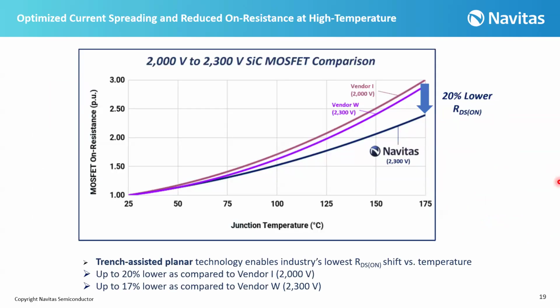Here are the resistance or temperature coefficients from room temperature to 175 degrees C. We compare 2.3 kilovolt Navitas devices with the two other vendors, 2 kilovolts and 2.3 kilovolts. And obviously, we can see lower temperature coefficients compared to both vendors, 20% compared to one of them, and 17% lower than the other component. And this is one thing that I mentioned. We have better current spreading in our design, and also the drift layer has been optimized regarding the doping concentration and thickness for this lower temperature coefficient.